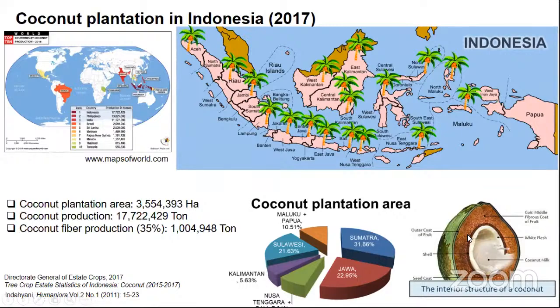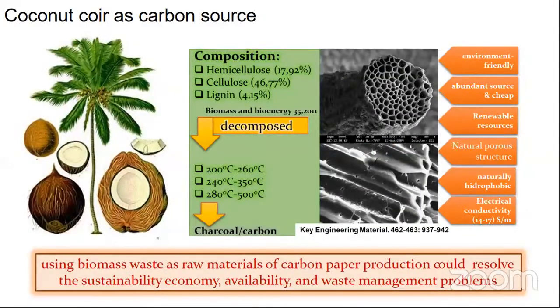Coconut coir is a lignocellulosic material that is primarily composed of cellulose, lignin, and hemicellulose. This lignocellulose compound degrades at different temperatures through carbonization in an oxygen-limited or oxygen-free environment to produce carbon-rich charcoal as residue. And this is the morphology of the coconut coir carbon observed by SEM.